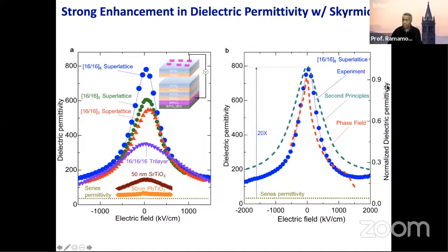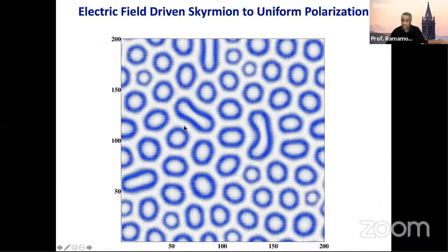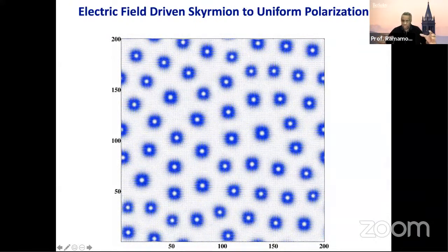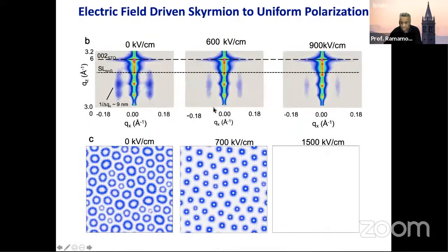On the right side, basically, I'm showing you the same data, but in this case, we have second principles, phase field data, and also X-ray scattering data, all of them superimposed. They're all basically telling you the same thing, that when you apply a field to this skyrmion array, you can start to see a change in the dielectric permittivity. But the first question is, where did this enhanced permittivity come from? And for that, we can go back to theory. This is phase field calculations, field driven. As you apply an electric field, you can see these skyrmions start to shrink, shrink, shrink, and boom, they'll go away.